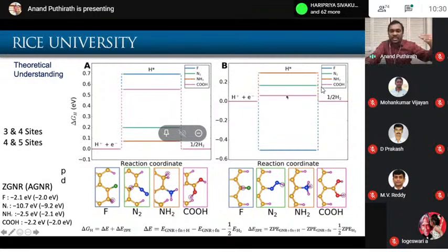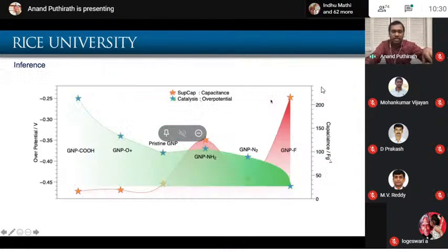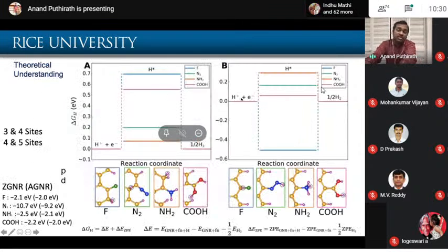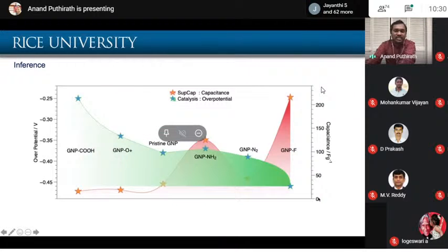Basically, COOH has the least delta G change during the adsorption desorption reaction, which simply says it will be a better catalyst, but it may be a bad supercapacitor electrode, because it is not adsorbed properly to have a better capacitance. And that was an interesting result.